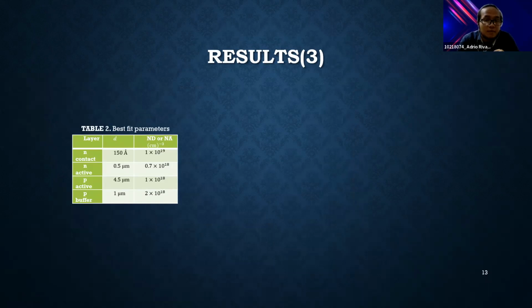Okay, this is the initial internal quantum efficiency of the gallium phosphide cell that we used in this research. And for the simulation result, we get the best fit parameters for this type of cell: the N contact with a thickness of 150 angstrom, the N active layer with a thickness of 0.5 micrometer, the P active layer with a thickness of 4.5 micrometer, and the P buffer layer thickness of 1 micrometer, with the dopant concentrations listed in Table 2.